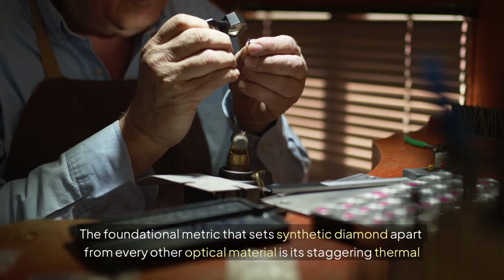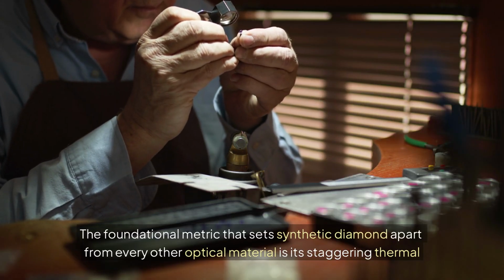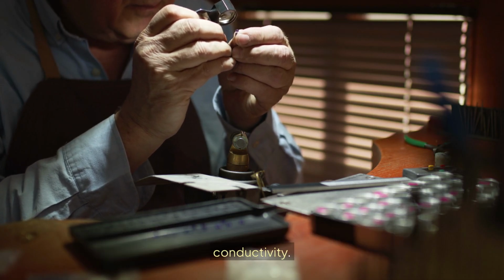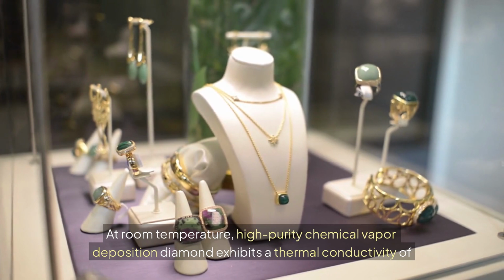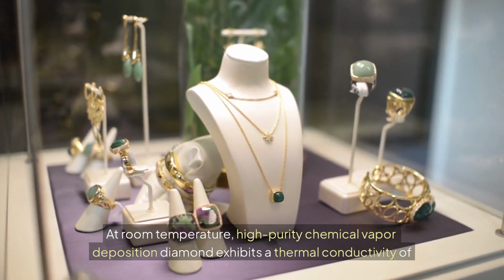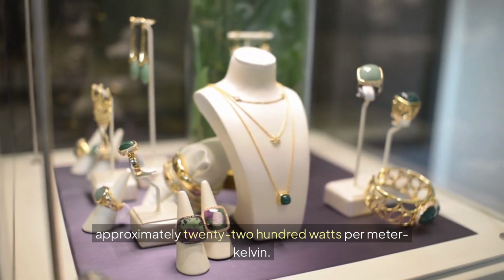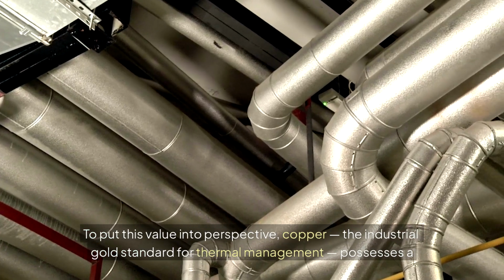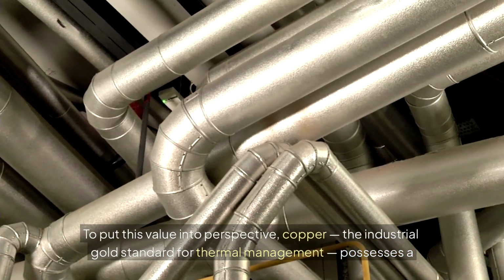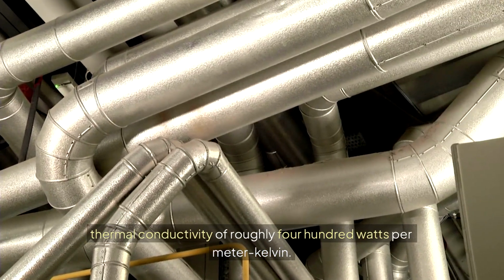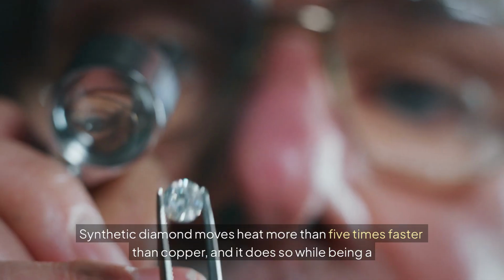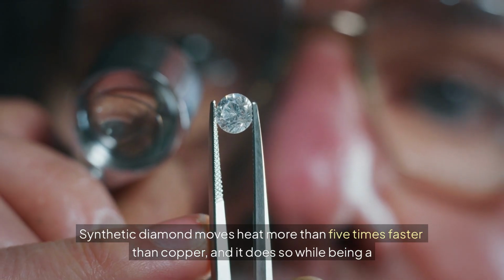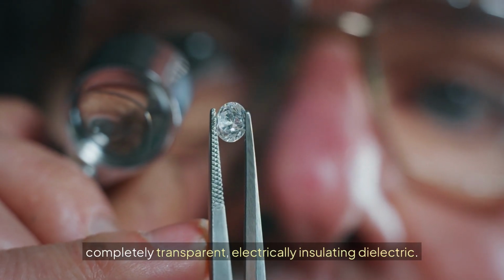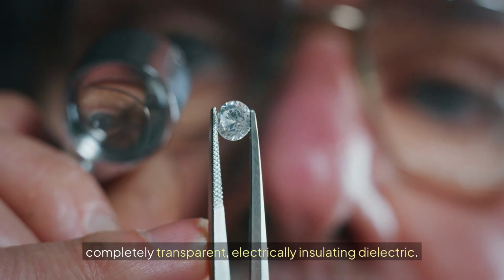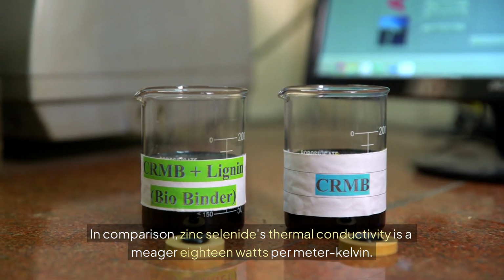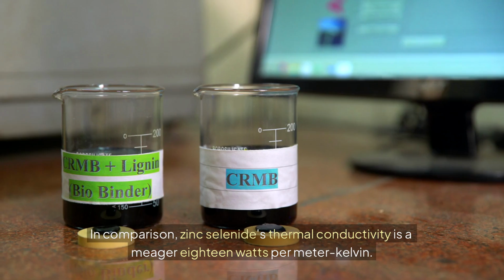The foundational metric that sets synthetic diamond apart from every other optical material is its staggering thermal conductivity. At room temperature, high-purity chemical vapor deposition diamond exhibits a thermal conductivity of approximately 2200 watts per meter Kelvin. To put this value into perspective, copper, the industrial gold standard for thermal management, possesses a thermal conductivity of roughly 400 watts per meter Kelvin. Synthetic diamond moves heat more than 5 times faster than copper, and it does so while being a completely transparent, electrically insulating dielectric. In comparison, zinc selenide thermal conductivity is a meager 18 watts per meter Kelvin.